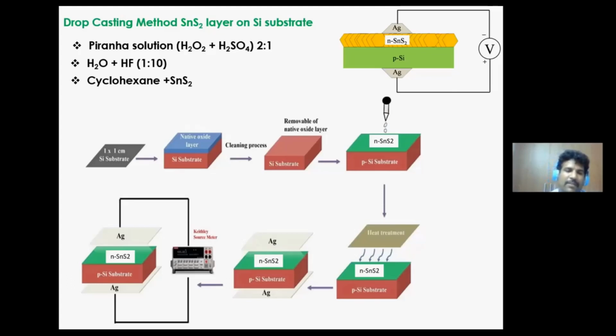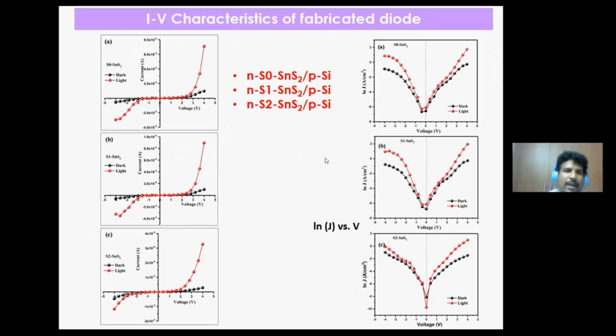So after that, silver is used to create an ohmic contact between SnS2 and the silicon substrate. After fabricating, we measured the IV characteristics of the three different solvent combinations of synthesized tin disulfide. All the materials have tin disulfide particles, but in the first one, S0-SnS2, there is a mixing of P-type and N-type, so automatically it disturbs the function of this diode.